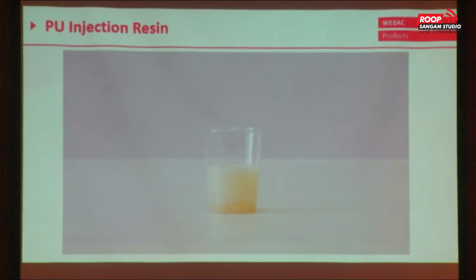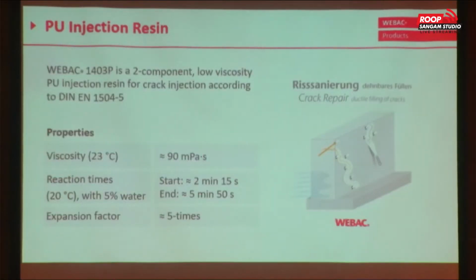So slightly foaming; for that product I calculate roughly 5-time expansion or 8-time expansion maximum. So this is what we talked about. You see the viscosity, roughly 90 millipascal-seconds (mPa·s). In areas where we have high temperatures, the viscosity will also be pushed down. I guess we speak about 60 millipascal-seconds (mPa·s) here, which is a really low viscous resin. Reaction time starts at 2 or 3 minutes, depending on the moisture inside the crack, and foaming ends roughly between 5 and 10 minutes.